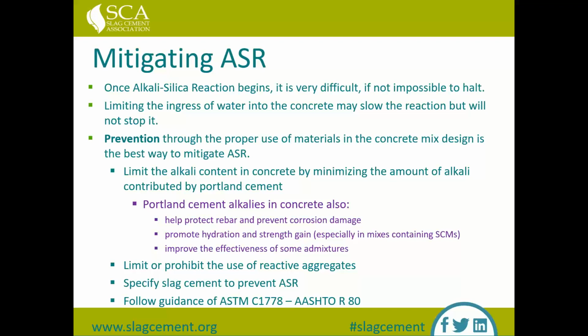But before we get there, with regard to limiting the alkali content in concrete, I wanted to note that while Portland cement alkalis can lead to ASR, they also have positive impacts on concrete. Portland cement alkalis can also help protect rebar and prevent corrosion damage. They help promote hydration and strength gain, especially in mixes containing SCMs such as slag. And they also can improve the effectiveness of some admixtures. So just wanted to note that there are some positives and negatives to Portland cement alkalis in concrete.